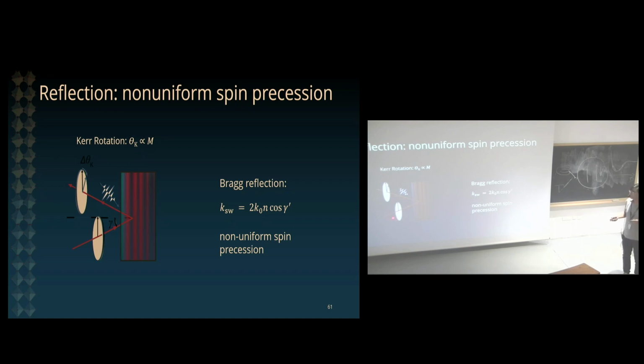However, if you now move to a Kerr rotation detection scheme, you can look at your experiment in a different way. Now you can think of a propagating spin wave in your system a little bit as a diffraction grating. Light that is being reflected here is going to be sensitive to a certain component of a propagating wave packet according to the Bragg condition. And so in a Kerr rotation geometry, in principle, you can also observe a non-uniform spin precession mode. This is routinely done for phonon modes. It is called Brillouin scattering for propagating phonon modes. But as far as we know, it was not tried before for spin waves.